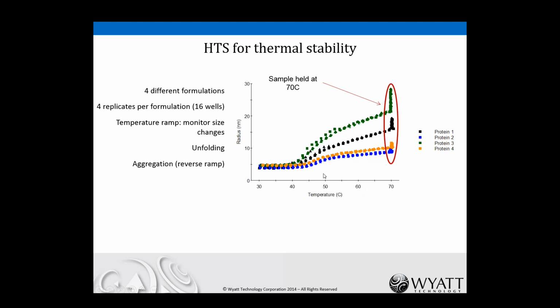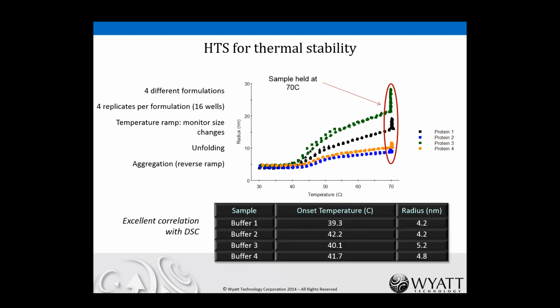I don't actually show in the graph here some additional data that you get from dynamic light scattering. That is the count rate. The count rate is static light scattering, essentially. And because static light scattering is proportional to molar mass, what we would see here is that where there's unfolding, the average molar mass does not change. And so there's a change in size, but no change in average molar mass. That indicates unfolding. And then later on, when you get to aggregation, the molar mass does increase. Therefore, the count rate will increase. And that will give us a nice indication of when we transition from unfolding to aggregation. Again, these data correlate very nicely with other techniques, such as differential scanning calorimetry.